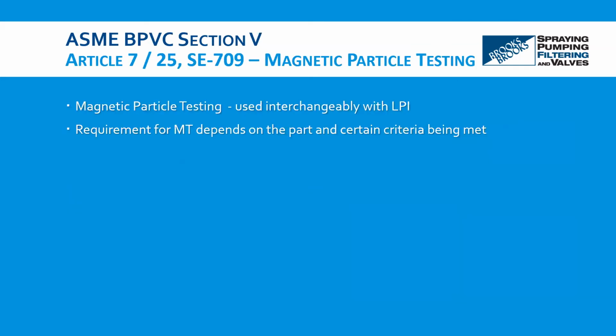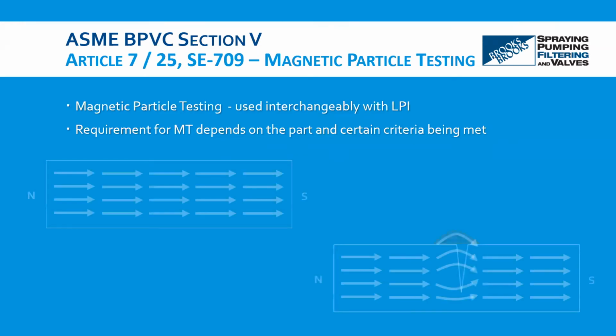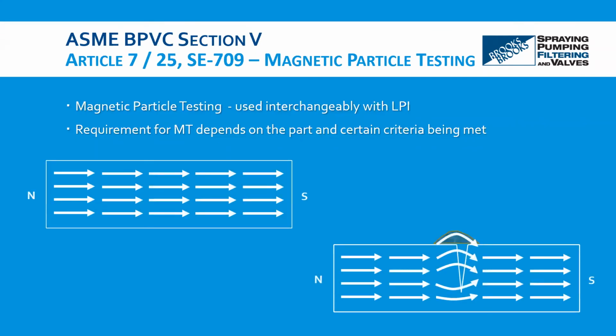And now on to magnetic particle testing. It's similar to liquid penetrant testing, and magnetic particle examination is frequently used as an NDE method, owing in part to its low cost to perform the test. However, it should be noted that it's only contingent on the material being ferromagnetic. If the material cannot be magnetized, then this test won't work. Mag particle testing checks for surface discontinuities, but it also reveals discontinuities slightly below the surface.